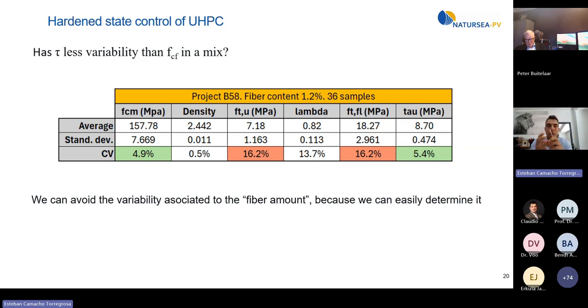Here I am showing the result of 36 samples of concrete, 1.2% of fibers, concrete used for the same project. You can see that the variability of the compressive strength is 4.9%. For the tensile strength, FTU, or for the flexural strength, it is 16%. Why? Because in the samples of the quality control, the fiber orientation is different. And sometimes the fiber content also, logically, is different because there is some statistical variation.